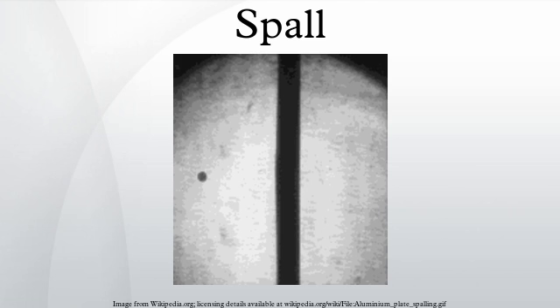In the case of actinide metals, the material expands so strongly upon exposure to air that a fine layer of oxide is forcibly expelled from the surface. A slowly oxidized plug of metallic uranium can sometimes resemble an onion subjected to desquamation. The main hazard arises from the pyrophoric character of actinide metals which can spontaneously ignite when their specific area is high. This property, along with these elements' inherent toxicity and radioactivity, make them dangerous to handle in metallic form under air. Therefore, they are often handled under an inert atmosphere inside an anaerobic glove box.